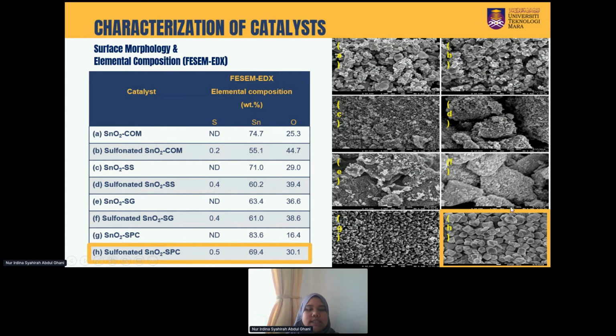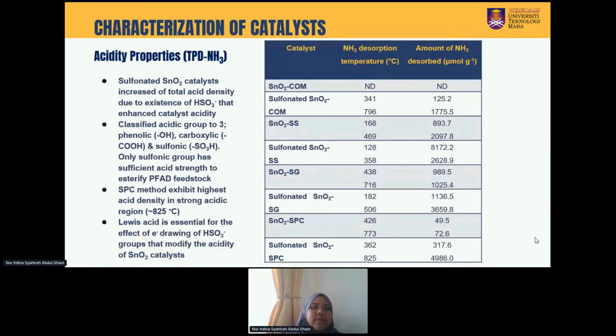This indicates that the sulfonated SnO2 SPC is the best one from the FESEM-EDX. For the acidity properties, initially it indicates that the sulfonated SnO2 catalyst increases the total acid density due to the existence of sulfonic ions that enhance the catalyst acidity, which indicates that the SnO2 SPC sulfonated method also exhibits the highest acid density in the strong acidic region. This is essential for the effect of electron drawing from the sulfonic group that modifies the acidity of the SnO2 catalyst.